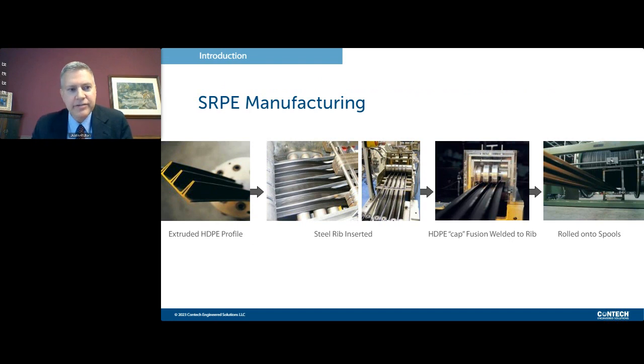Many people ask, well, how do you get the steel inside of the plastic? And that's a great question. The manufacturing process starts out with melting the resin down and extruding it through a die to create a profile. And there's 3 different sizes of profile depending on the diameter of pipe that you want to make. Each profile has vertical legs, and the steel ribs are laced in between these vertical legs, and then an HDPE cap is fusion welded on top to fully encapsulate and seal the steel inside the plastic.